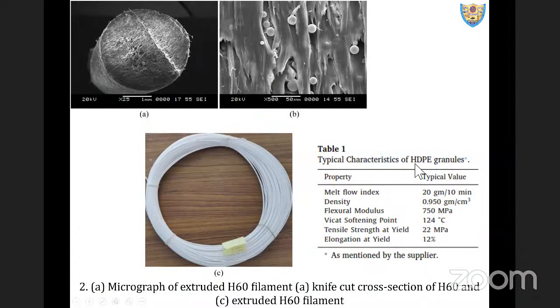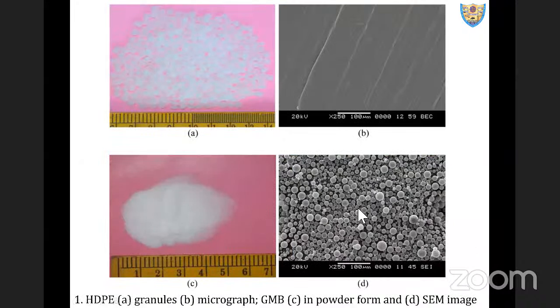So in high density polyethylene, we prepare a blend of glass in HDP matrix. What we are going to look at henceforth is manufacturing of a sandwich in one go using 3D printing. Now for manufacturing of a sandwich using additive manufacturing or 3D printing, we need to use two materials, one for core, C-O-R-E, and another for skin. So here we are keeping the skin as high density polyethylene and the core as the mixture of these two.